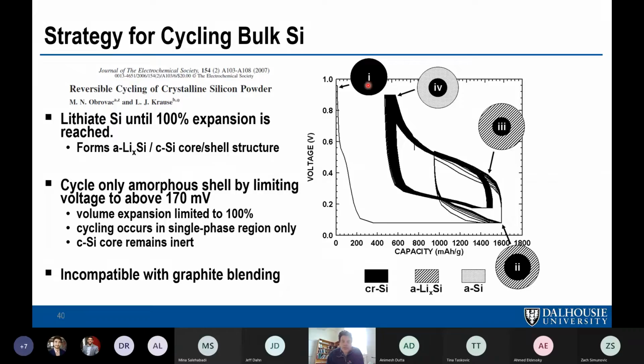If you remember this first lithiation of crystalline silicon, here we're starting with crystalline silicon. That's a two-phase region between crystalline silicon and lithiated amorphous silicon, and it happens at 170 millivolts. So if you go along here and stop it when you get to 100% volume expansion, then you form a particle that has a core that's unlithiated silicon and the outside is lithiated amorphous silicon. And then you could do some fancy conditioning cycles that are discussed in this paper to better form this outside amorphous layer. And you get this core-shell type particle. And if you stay above this 170 millivolt two-phase region voltage, you'll never lithiate the core again.